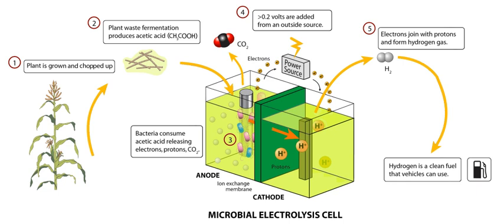Materials: the anode material in a MEC can be the same as an MFC, such as carbon cloth, carbon paper, graphite felt, graphite granules or graphite brushes. Platinum can be used as a catalyst to reduce the overpotential required for hydrogen production. The high cost of platinum is driving research into biocathodes as an alternative. Or as another alternative for catalyst, stainless steel plates were used as cathode and anode materials. Other materials include membranes, although some MECs are membraneless, and tubing and gas collection systems.